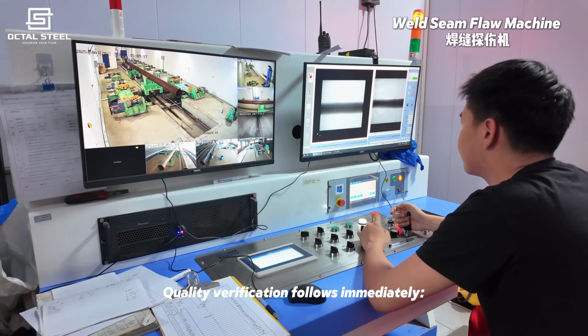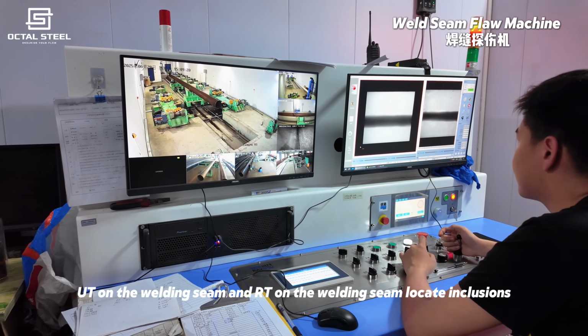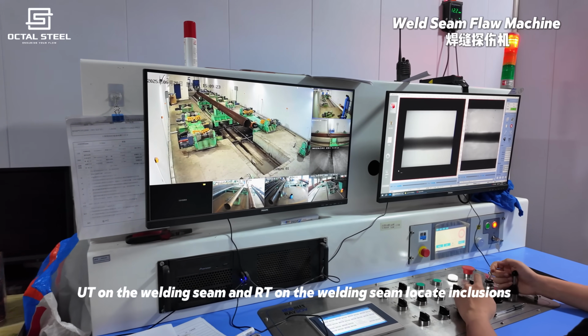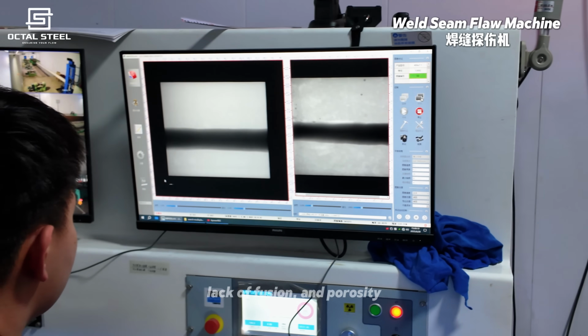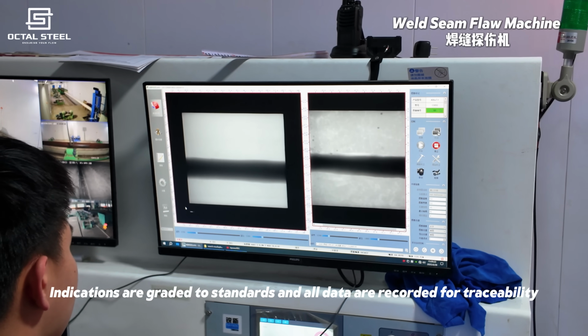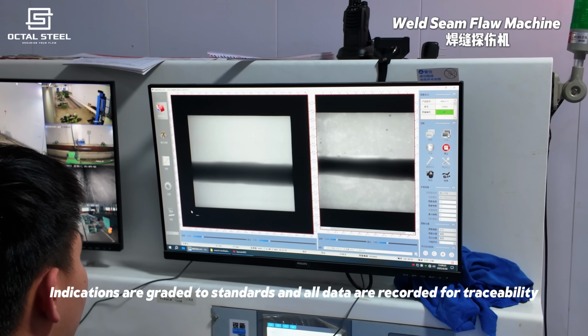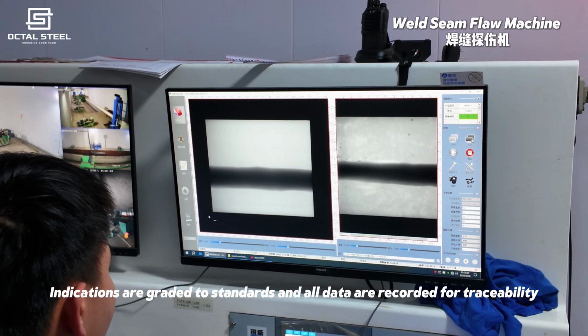Quality verification follows immediately. UT on the welding seam and RT on the welding seam locate inclusions, lack of fusion, and porosity. Indications are graded to standards and all data are recorded for traceability.